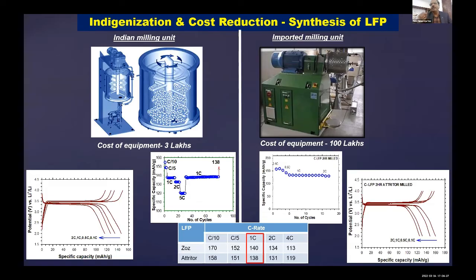So each particle of LFP is coated with carbon to draw the current from the electrons generated because of lithium intercalation, deintercalation. That has to go to the current collector, which is the aluminum or copper foil, whether it's a cathode or anode. And second, you have to make the size of the lithium iron phosphate into nano size because it is an insulator, the lithium ion and electron cannot diffuse over a long distance. So the diffusion length will come down when you have a smaller particle size. This is the one key challenge for making this material.